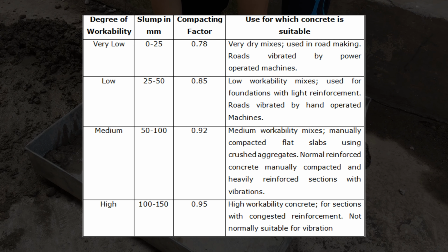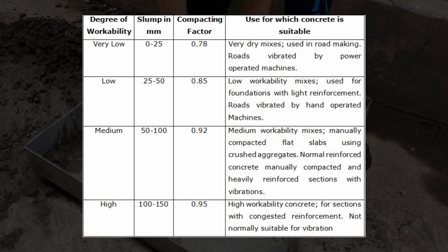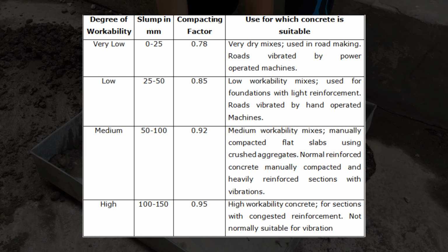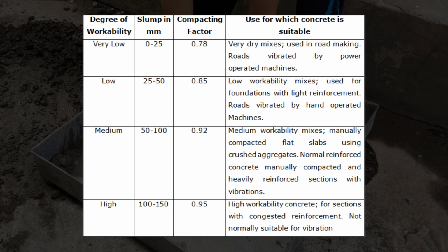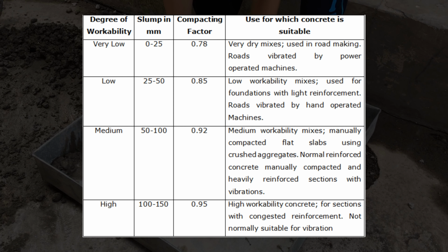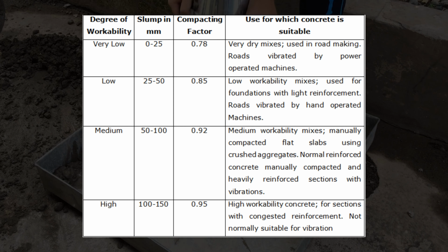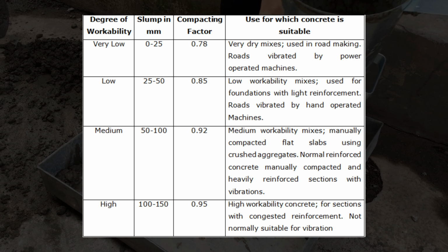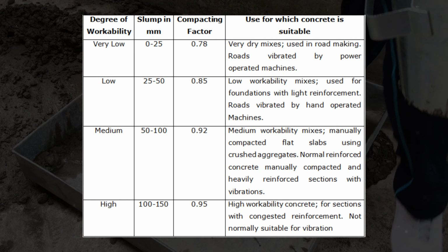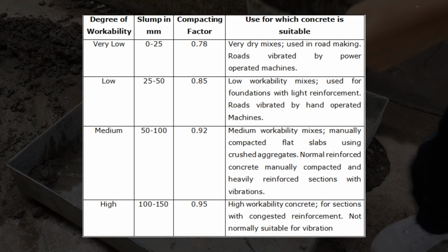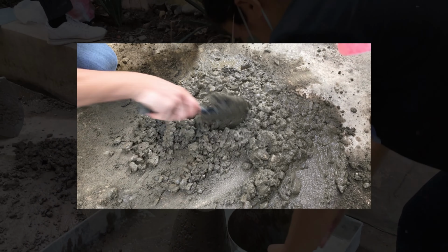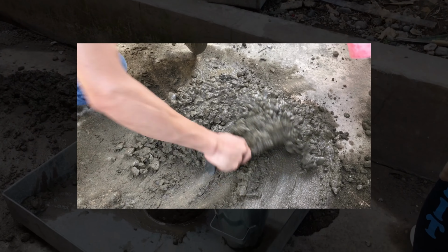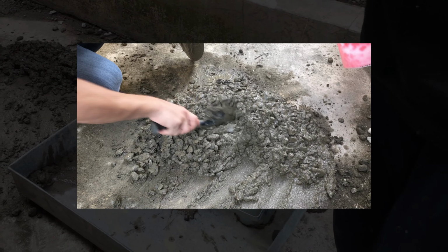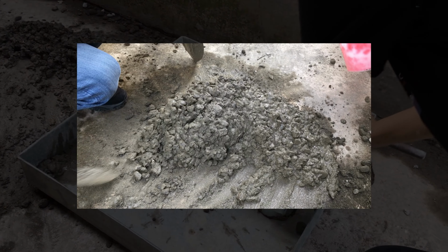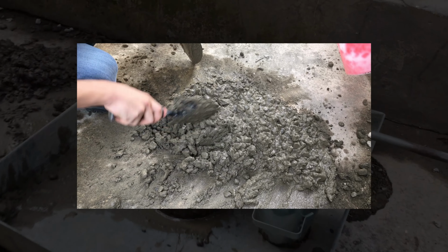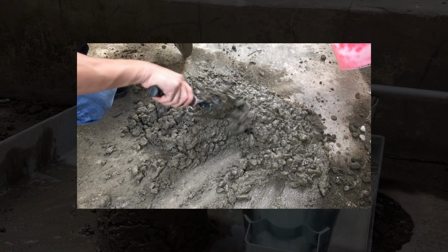Based on the standard specifications shown in the table, our slump value falls within the range of 0 to 25 mm, which is typically associated with the dry mix used in road making. Additionally, a compacting factor of 0.78 is mentioned, which may further indicate the dryness of the mix. A dry mix typically has a lower water-to-cement ratio, resulting in a stiffer concrete mixture. This type of mix is often used for road construction to achieve better compaction and durability.